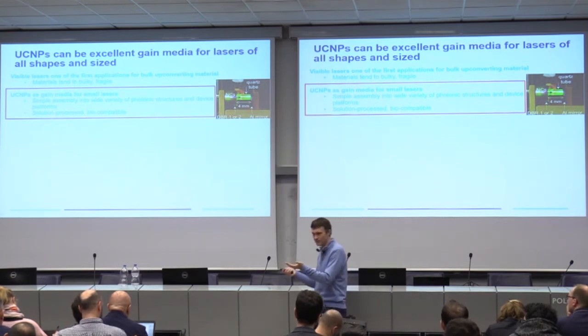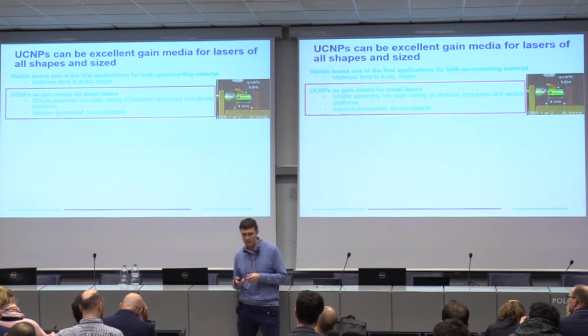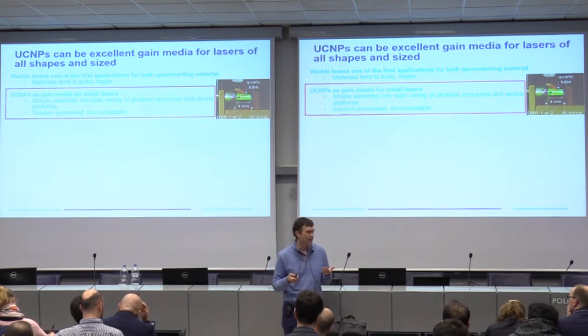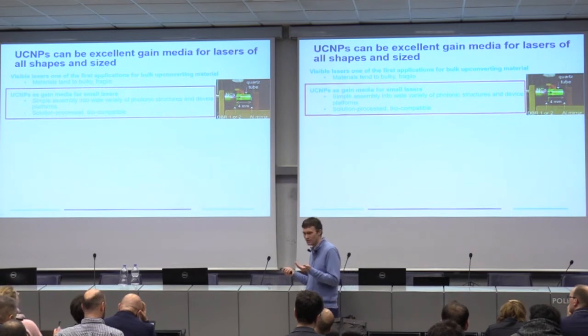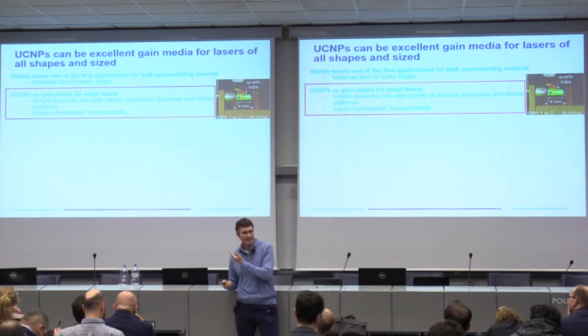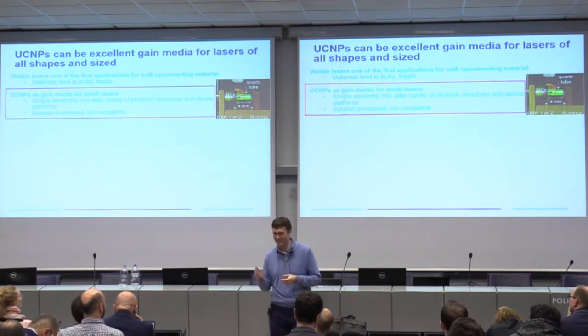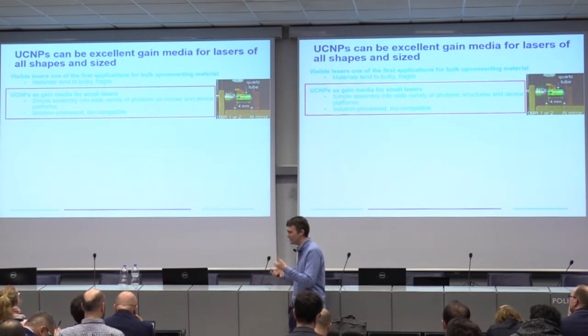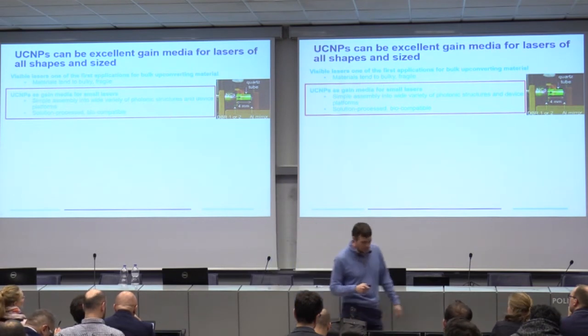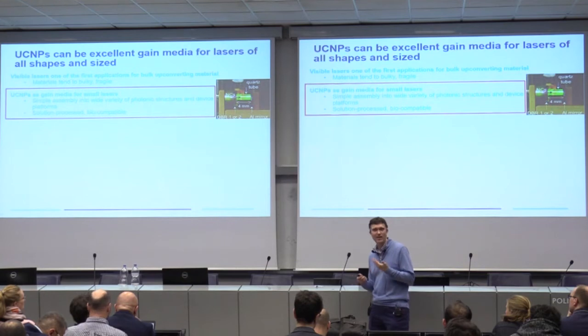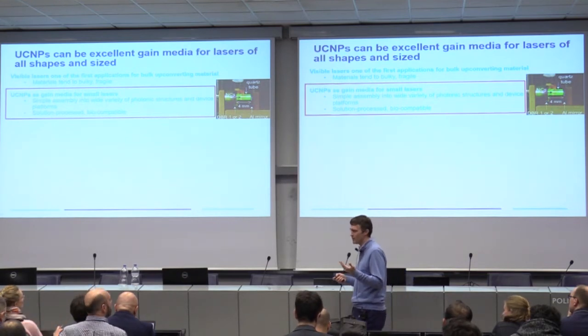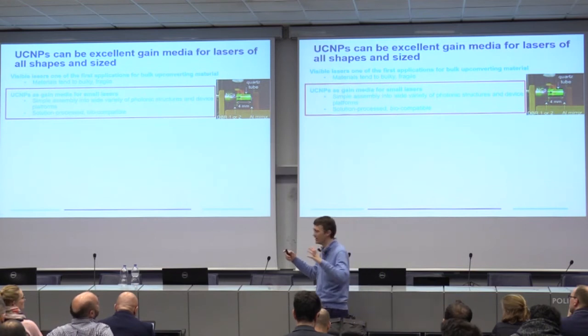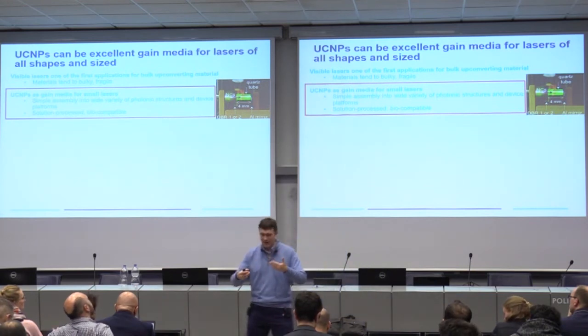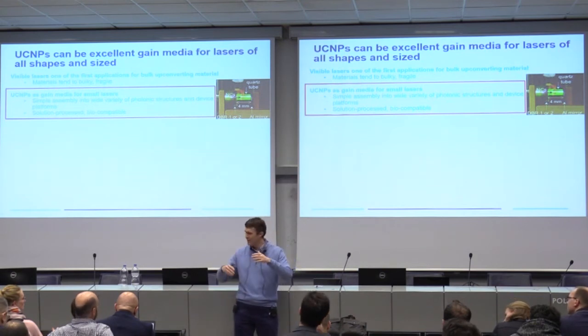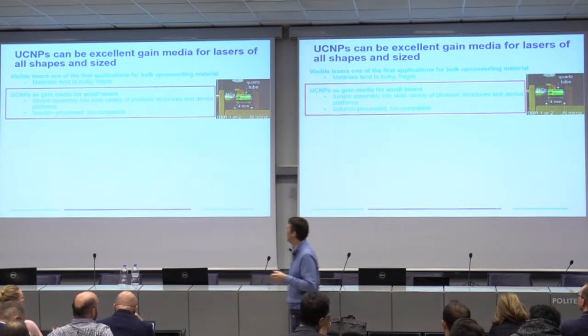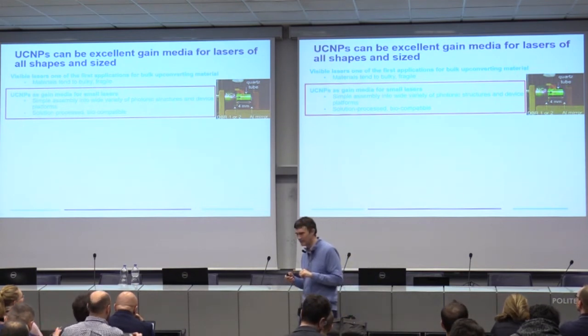The whole point was that most of the lasers that had been made at first worked in the red and the infrared. And what people wanted was other colors too, especially visible colors. And so this was maybe the most efficient way to get those. Nowadays, people have very efficient doubling crystals and things. I think that's what's in here, a 1064 or something that gets doubled. But that was the main motivation for making these materials. So there's a lot of literature on people making lasers out of these upconverting materials. They're just out of these very large bulk crystals that turn out to be relatively difficult to mechanically manipulate, to fabricate, to etch, right? They're very brittle and they're large. And so that development stalled a little bit.